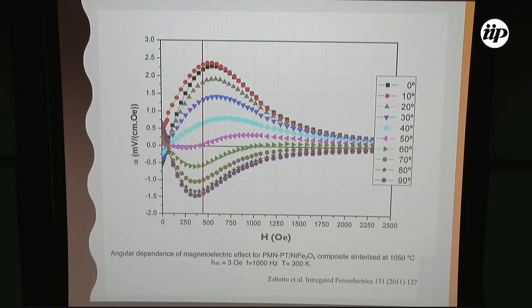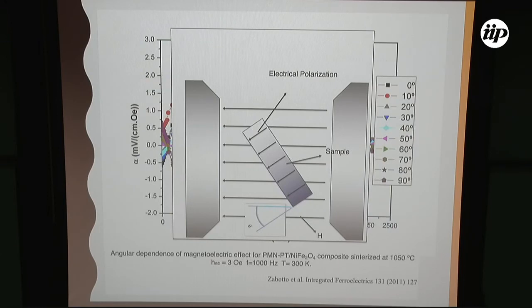If you study the magnetoelectric effect as a function of the angle of the polarization of the sample, polarizing the sample at around 2 kilovolts per centimeter, a change in the values of the magnetoelectric effect is observed as a function of the field and the angle. There is a maximum at 0 and 10 degrees is absolutely the same, and then as it decreases there is a change of sign of the magnetoelectric susceptibility. The configuration is the electrical polarization of the sample and the change of the direction, the change of position of the sample as a function of the applied magnetic field.